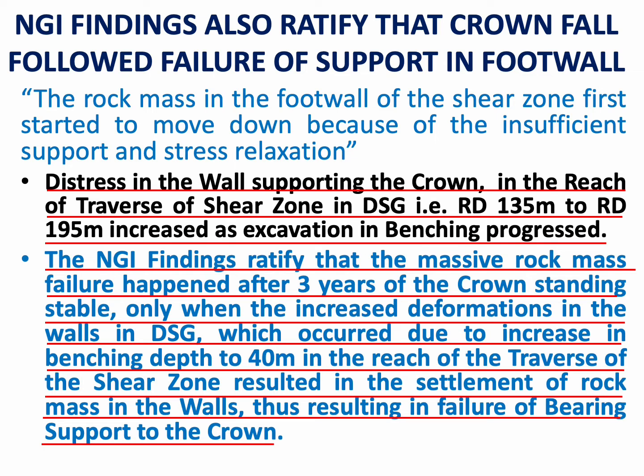So NGI findings ratify this observation that after 3 years, when the benching was progressing in the reach which is the traverse of the shear zone in the walls, and benching had progressed to around 40 meter in its depth, then there were settlements of the rock mass in the walls happening, which resulted in failure of support in the bearing for the crown.